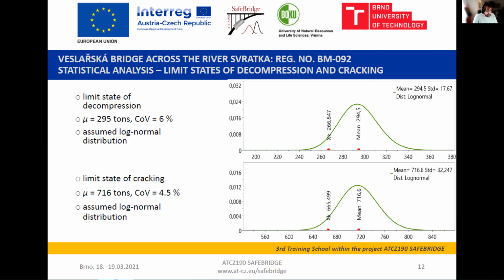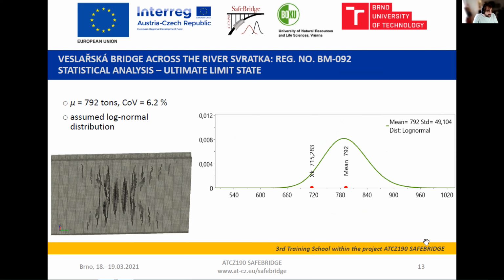If we look at the second quantity of interest, the limit state of cracking, the first occurrence of cracks, we have a mean value of 716 tons and a coefficient of variation of 4.5%. Again, we assume log normal distribution. And finally, the ultimate limit state, meaning the load leading to failure of the structure. We have 792 tons and a coefficient of variation of 6.2%. Note that these are all mean values. These are not design values. Those will be much lower.